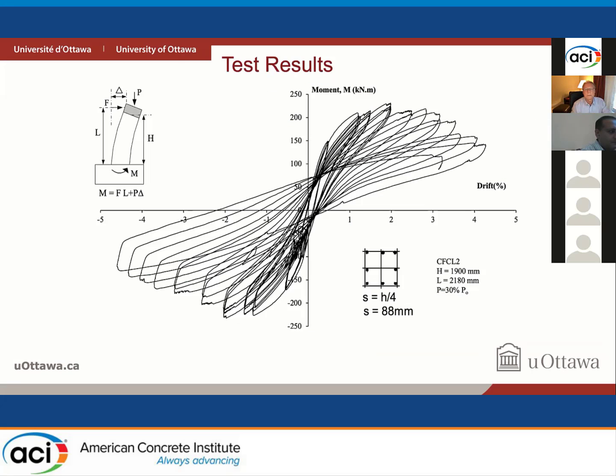If we look at test data, I have reproduced only two hysteretic behaviors. We were able to get some deformability. We went up to 2% without any strength decay, and at 2% concrete started crushing. And then gradually we started observing strength decay, but it is noteworthy that the unloading branches were passing almost through the origin, which indicates obviously that they remained elastic. So this was the restoring capability of FRP that we observed.